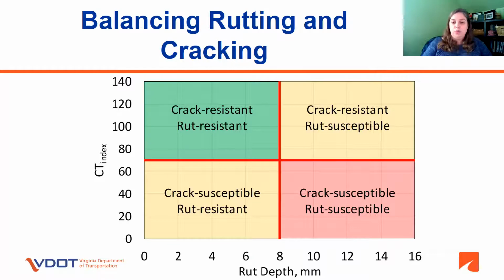If we have too much asphalt in the mix, or too much rutting in our testing, what we find is that we may be more crack resistant, but we will have rutting susceptibility issues. If the CT index is very low, we're going to have a crack susceptible mix, though these mixes may be very rut resistant.